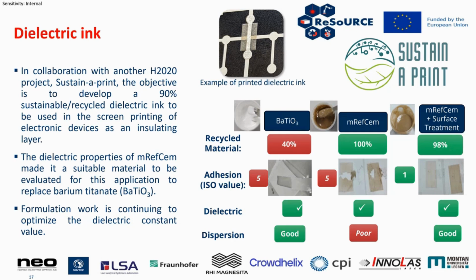And what we found was we could mix this in. It could give us good dielectric properties, but the actual dispersion itself was poor and the adhesion was poor, which was the same for the reference barium titanate. But when we surface modify this material, we can improve the adhesion to a much greater degree, and it actually doesn't delaminate and flake off like the previous formulations, and we get good dispersion and we maintain the dielectric properties. So this was a very good win for the Sustainaprint project because they could use up to 98% recycled materials in their final product, which was the main target of their project.